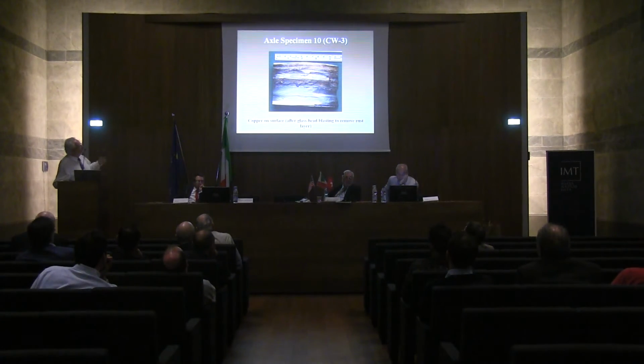And here's axle specimen 10 or CW3 coating. And you can see copper on the surface. Now, this was glass bead blasted, not shot blasted, but glass bead just to remove the rust. And you can see the cracks in there.